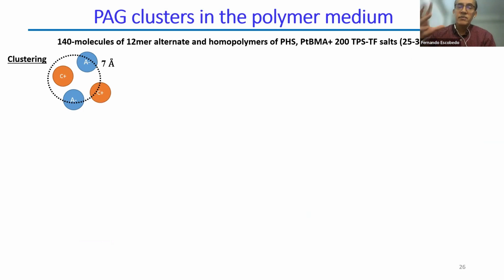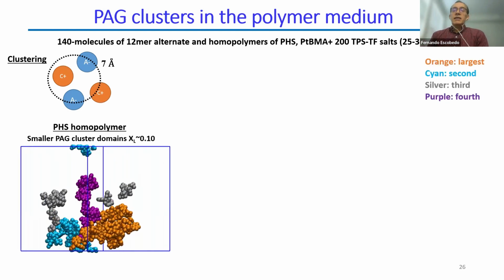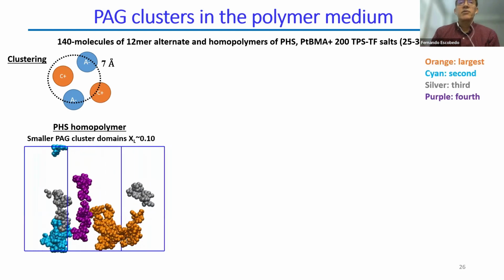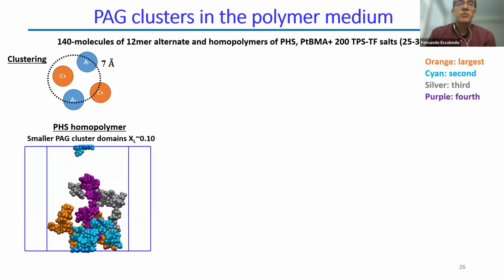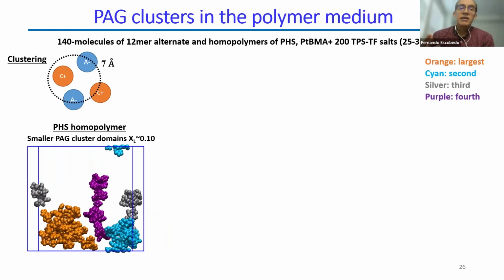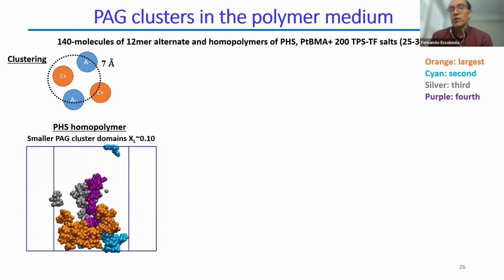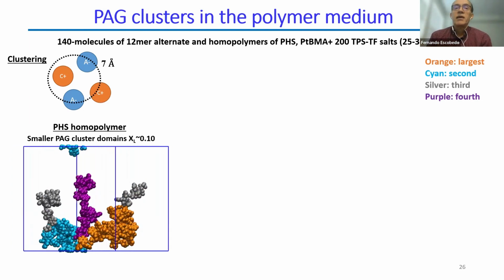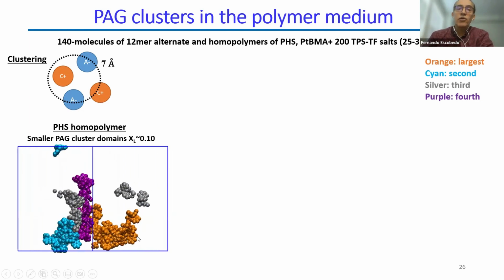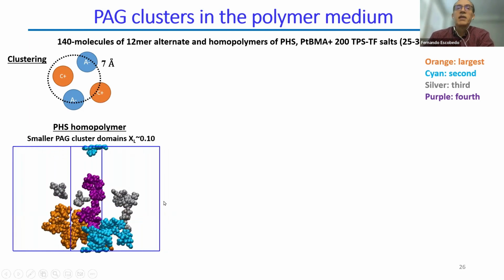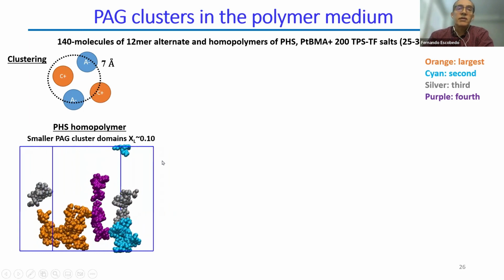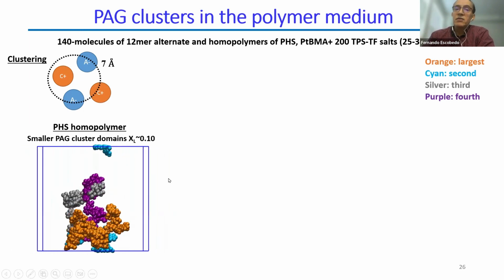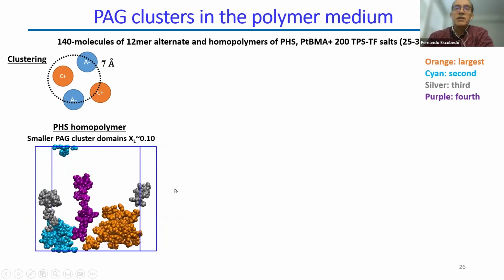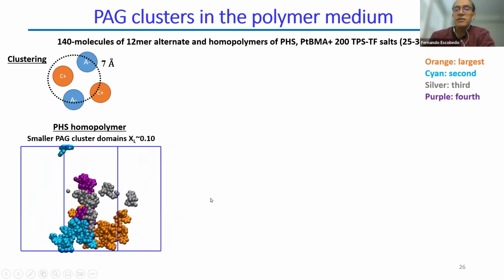We have to define, of course, some kind of distance threshold to decide whether the ions are close enough to be clustered. In doing that, you can analyze, for example, what happens with these salts in the PHS homopolymer. What I'm showing here are the largest clusters you will see. I'm not showing you the polymer just to make things clear. You should pay special attention to the orange cluster, which is the largest one of them. Our calculation shows that this large cluster is not that large, in the sense that only 10% of all the salts are in that cluster.